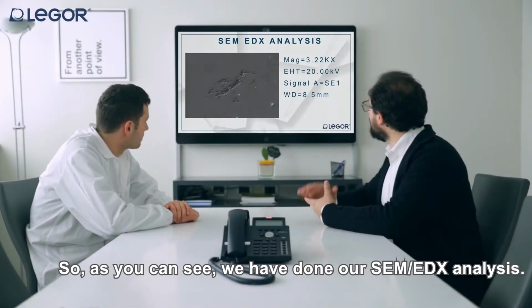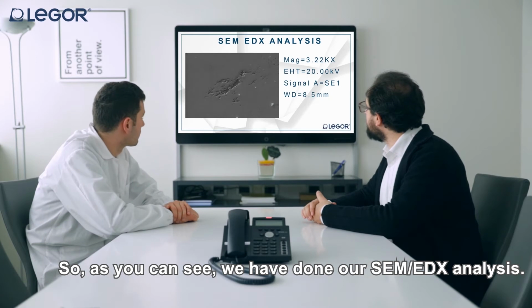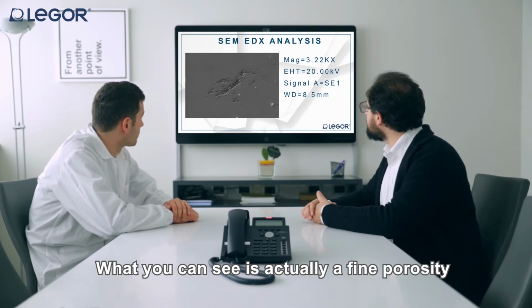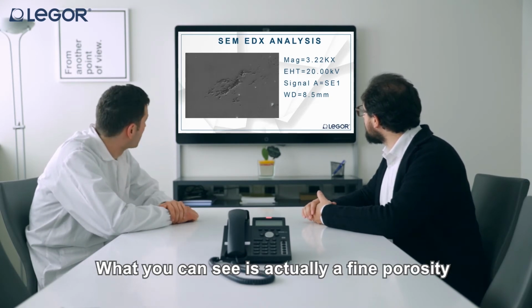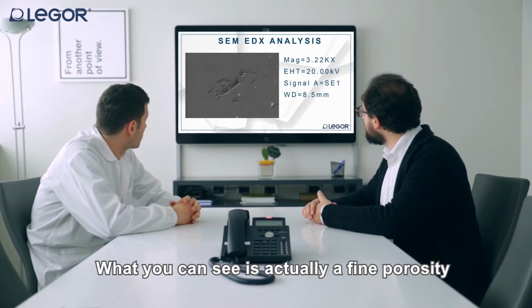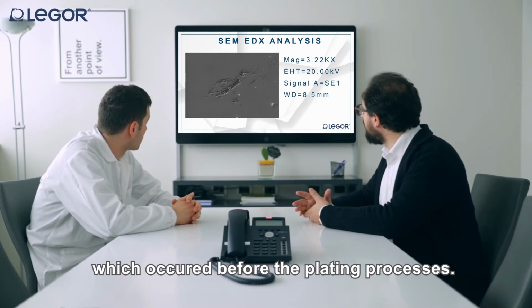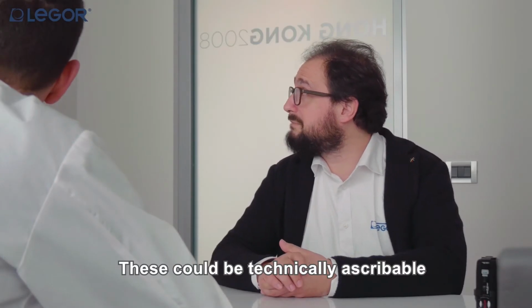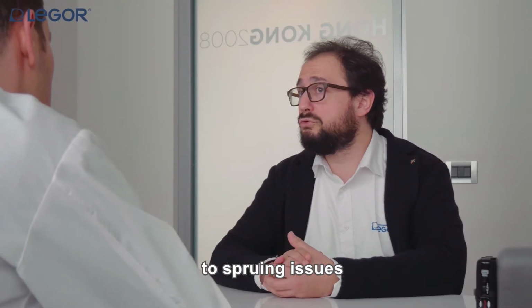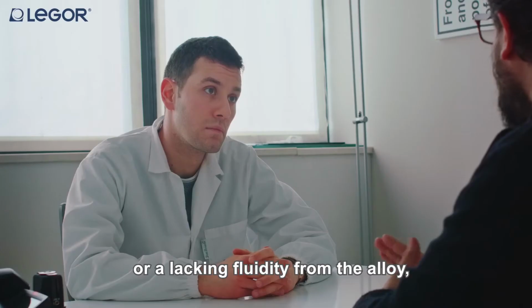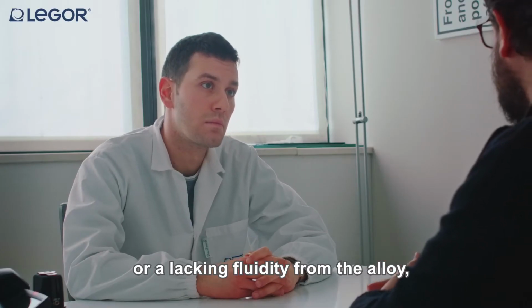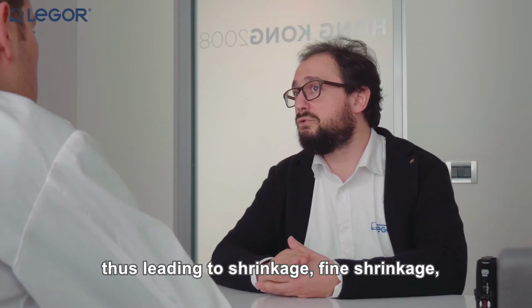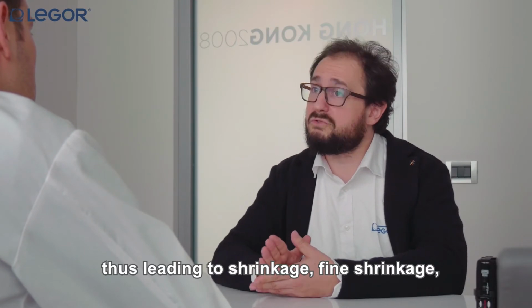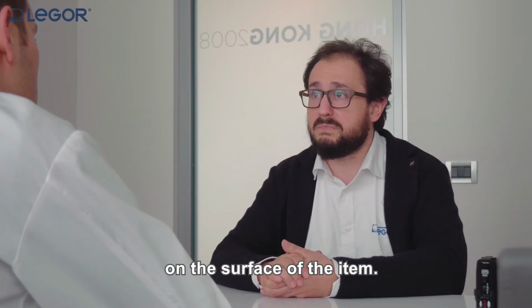So as you can see, we have done our SEM EDX analysis, and what you can see is actually a fine porosity which occurred before the plating process. This could be technically ascribable to sprueing issues or a lacking fluidity from the alloy, thus leading to a shrinkage, a fine shrinkage on the surface of the item.